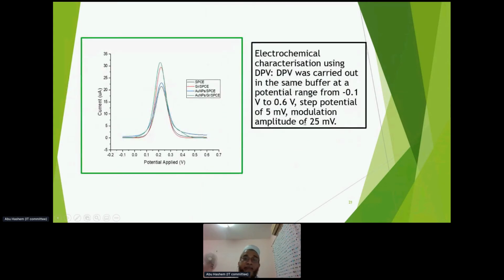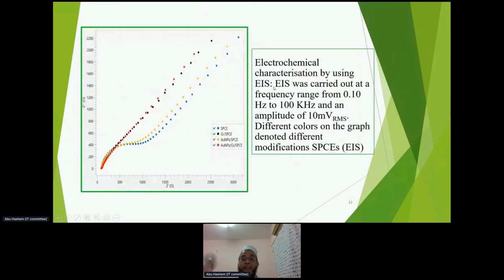Also, we characterize it with DPV, with the same pattern of result, and we also characterize it with electrochemical impedance spectroscopy. Here the red color indicates that our target modified electrode is showing the least impedance, that is, more conductivity.